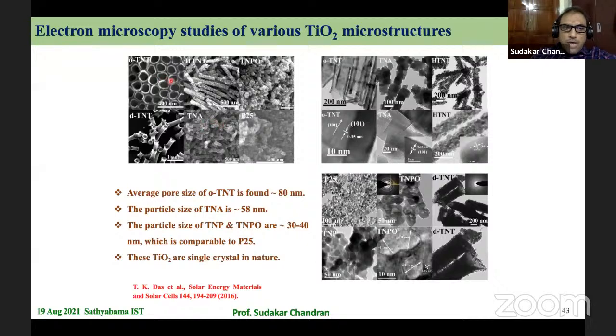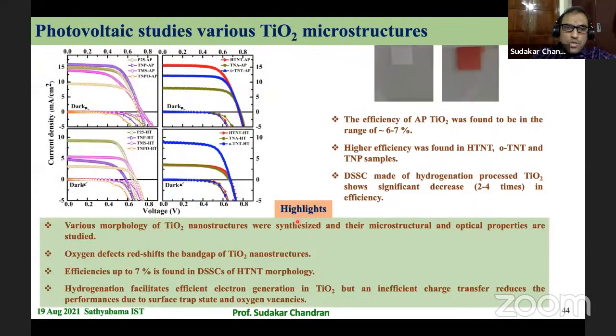Okay, so we have tested nanotubes of TiO2, and then these kinds of hierarchical nano bundles or random porous structures, the tubes made by Sol-Gel process, and so on. So in all these structures, the efficiency of the solar cell varies to a large extent. And we found out that whenever the oxygen vacancies are large, the efficiency goes down. But then the efficient way of electron transfer does happen in that material, but the efficiency goes down because the electrons are not effectively taken out.